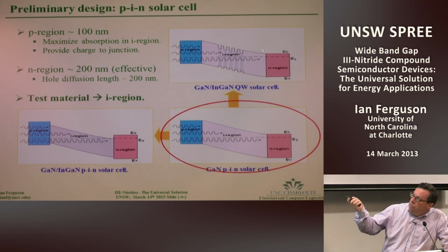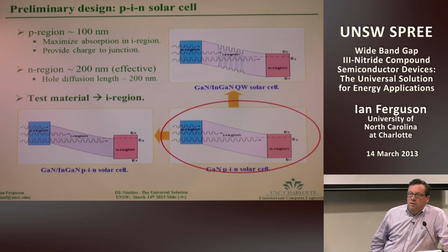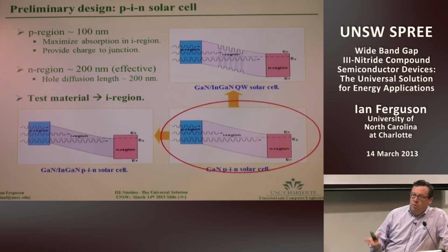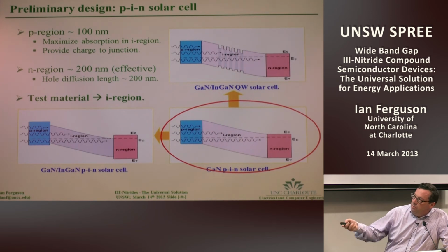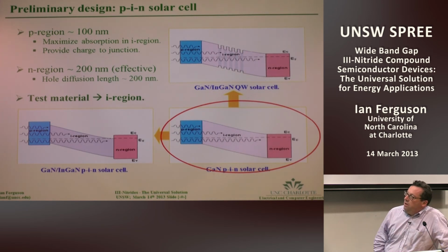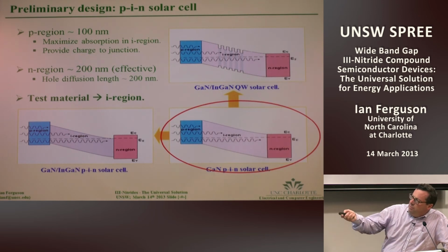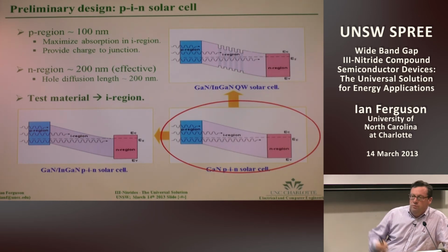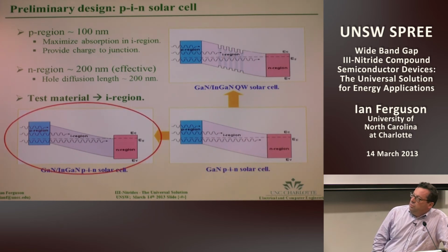We stayed away. We did do some quantum well devices, but even within the solar community, I'm still not sure that people necessarily like those devices. They localize carriers, but you can't always efficiently extract carriers. So I think a simple homojunction device or some type of simple heterojunction device is preferable. These types of devices we'd done before for UV detectors, so we had more experience with this type of device.